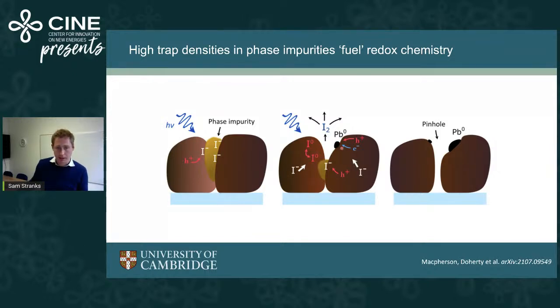these lead 0 remnants. And so what the net effect is, you start eating away at this phase impurity grain, and eventually start eating away at the perovskite grain, leaving these pinholes and also these signatures of metallic lead 0 there as well.